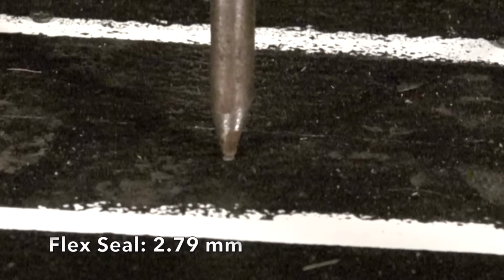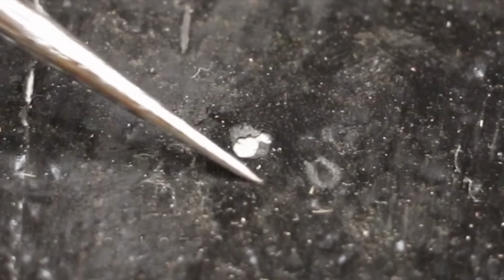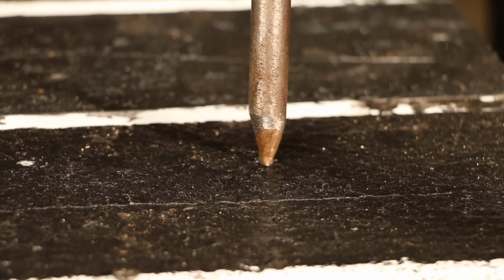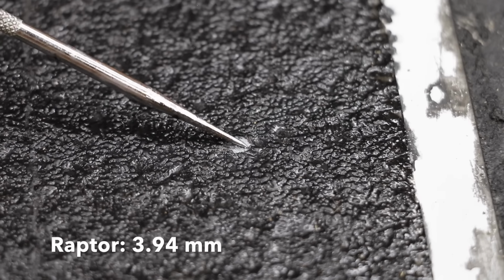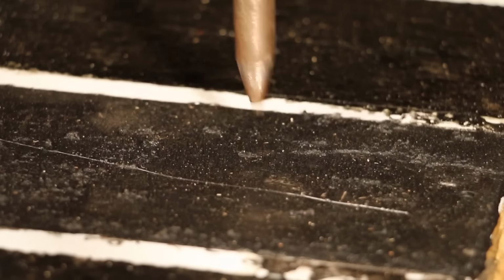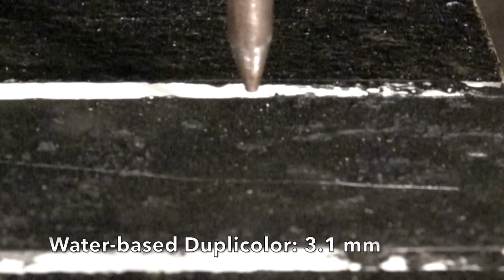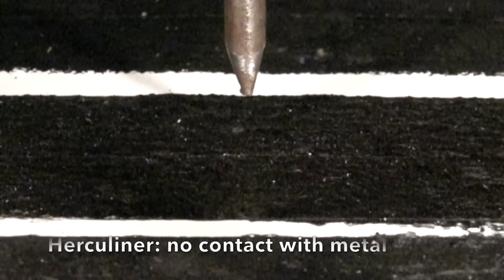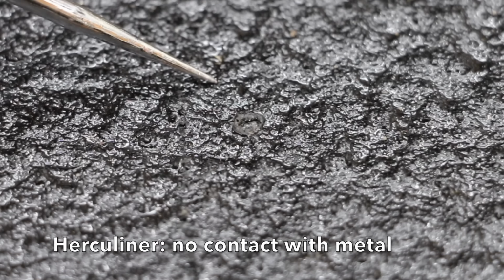Flex Seal, which has very good adhesive properties, only had 2.79 millimeters of damage. The Raptor experienced slightly more damage than Flex Seal at 3.94 millimeters. The size of the damaged area with the water-based Dupli-Color was 3.1 millimeters. The Herculiner did by far the best yet. The steel rod left a mark but did not fully penetrate the bedliner material.